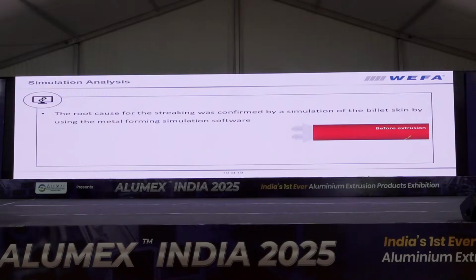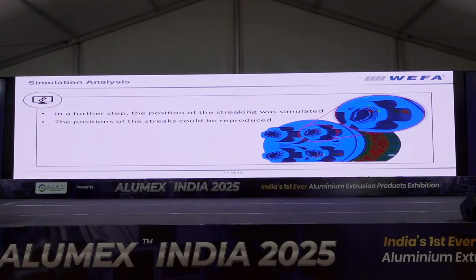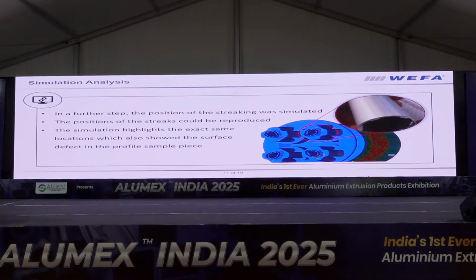What we tried to have before extrusion, and then we have seen that billet skin, even after only 40% of the entire billet length of 1.2 meter, was already sucked into the system, and remaining billet skin enters into the die stack here. In a further step, the position of the streaking was simulated, so you could see here even some of the streaks we were able to simulate by the software. Also again here in a closer view it could be reproduced. The simulation highlighted the exact same location which we have seen during extrusion.